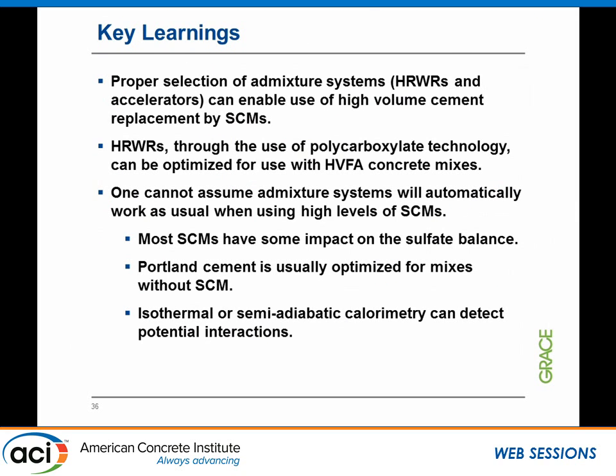So all in all, in here, we want to present to you that the proper selection of admixture systems with the dispersing systems and the accelerators are going to be critical to enable us to use this high volume SCM. High range water reducer through the use of polycarboxylate technology can enable the optimized use of the high volume fly ash. And also, we cannot assume that an admixture system will automatically work, particularly in using high levels of SCM. We see issues with sulfate balance. We see more issues with cement interaction, and therefore the use of calorimetry really should be our friend.